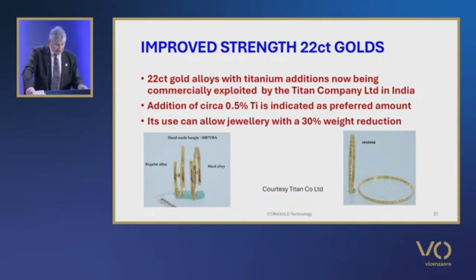So 22-carat gold alloys I spoke about last year demonstrated that titanium alloy additions act as a grain refiner and allow substantial age hardening. And we saw in that table some results. The commercial use of a 22-carat gold alloy strengthened by titanium, based on this work by the Titan company in India, has allowed jewellery products to be marketed that show a 30% weight reduction compared to conventional 22-carat gold alloys. The figure on the bottom left of the slide shows a hollow bangle in their new alloy. That on the right shows a solid bangle. And my understanding is it's about 0.5 weight% titanium is the alloying addition.